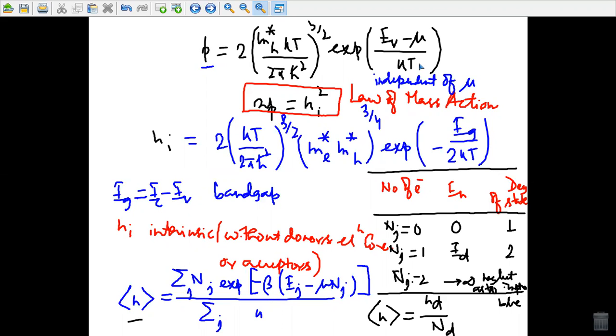Since the density of states in the valence and conduction bands is essentially unmodified by the presence or absence of donors and acceptors, the equations for n and p are valid with or without donors or acceptors. So multiplying n and p, we find ni squared, where ni is 2 kT over 2 pi h-bar squared to the power 3 by 2, (m star mh star) to the power 3 by 4, exponential of minus Eg upon 2kT, where Eg is EC minus EV, simply the band gap, and ni is the intrinsic, or without donors or acceptors, electron concentration. This equation is sometimes called the law of mass action and is generally true since it is independent of the chemical potential mu.